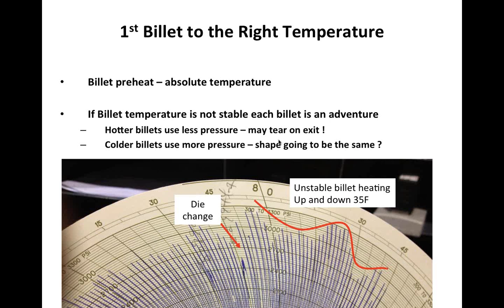Accuracy of billet temperature. The billet temperature has to be within plus or minus 10 degrees of our target. I think in today's world, with the capabilities of equipment, there's no excuse for not having a billet that's within 10 degrees of our target. As the billet becomes colder, it's harder to extrude because the flow stress of the billet increases. If we want to optimize our ram speed, we have to have control over billet temperature.